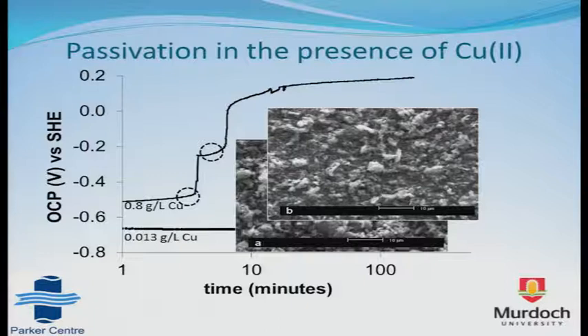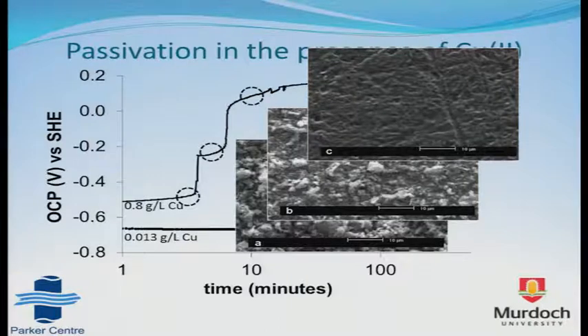Once all the copper is dissolved, what's left behind is just an iron surface, but it's actually passive, so it's covered by a thin oxide layer which prevents further reaction. And in this case, it happens within 10 minutes at 0.8 grams per litre of copper, but it can take place at 0.013 grams per litre at just longer times.